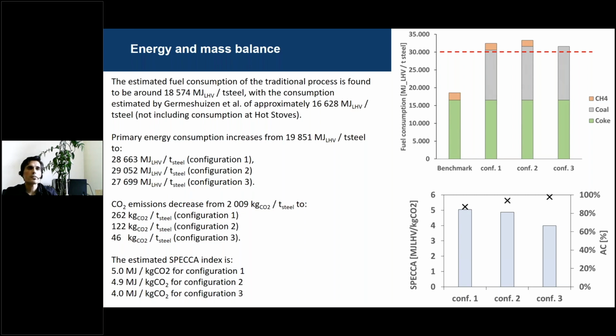Here in this figure, I reported the fuel consumption inside the steel industry, and as you can see, this is increasing from approximately 20,000 megajoule per ton of steel up to a value beyond 30,000 megajoule per ton of steel, because we need energy to regenerate the solid sorbent. With regard instead to the primary energy consumption, which is the fuel consumption plus the energy